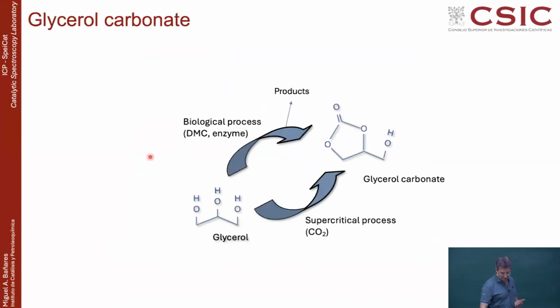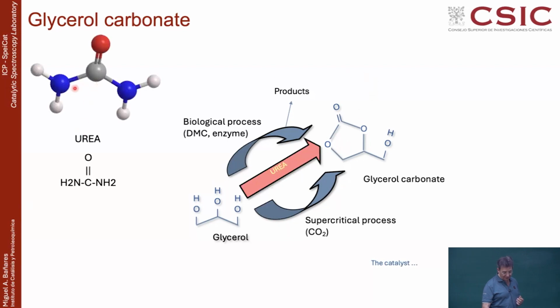And this is a product that basically can be made in different manners. Biologically, with enzymes, and then you will get glycerol carbonate. Or with supercritical CO2, and you get glycerol carbonate. Or you can use something that behaves like CO2, urea, which is also a byproduct. And if you use urea, the reactivity of urea is equivalent to the reactivity of CO2. Because in the end, with urea you get that CO group and 2 NH2 groups. The way it binds, for instance, to diols is the same way that carbon dioxide will bind to a diol. It will make a carbonate, and 2 ammonia molecules will come out. So you get glycerol carbonate and 2 ammonias.